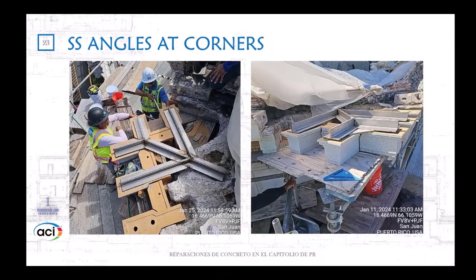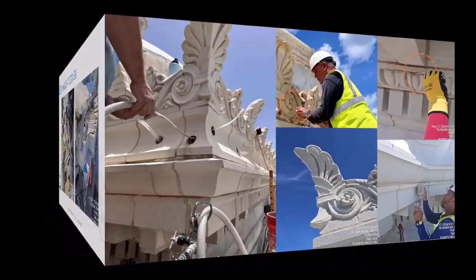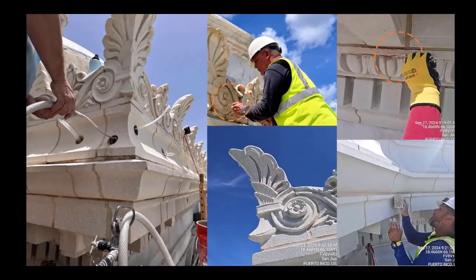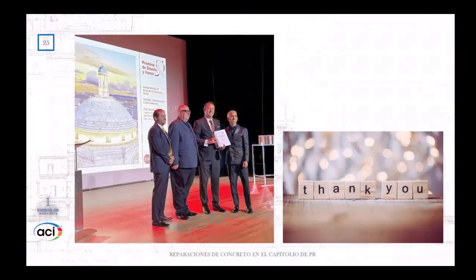The contractor made a redesign after we saw the extensive damage. This is on the corners. We needed to do some extra structural work. We used stainless steel angles and concrete beams, and it was injected. And I wanted to show these 2 pictures. At the end, artists with a small spatula finished the project, to make sure that all the ornamental terracotta matched the mix. And we received an award from the architects in Puerto Rico, and we're very humbled by the ACI award. Thank you.